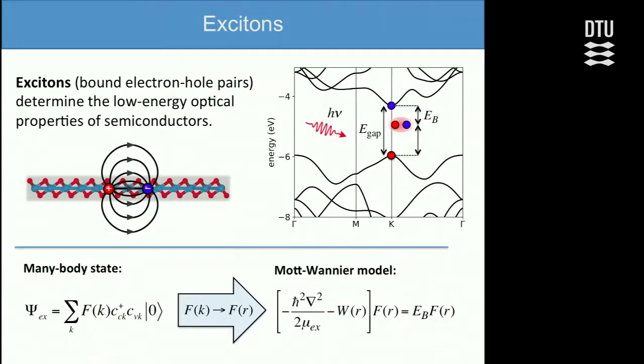We can take the expansion coefficients here, and then one can show that the Fourier transform of these expansion coefficients, which are defined in reciprocal space, satisfy this simplified Schrödinger equation, called the Mott-Wannier model. This is a drastic simplification, and if the screening is simple, just 1 over r times epsilon, as it is in 3-dimensional crystals with a dielectric constant, then this is just a screened hydrogen atom in 3 dimensions.